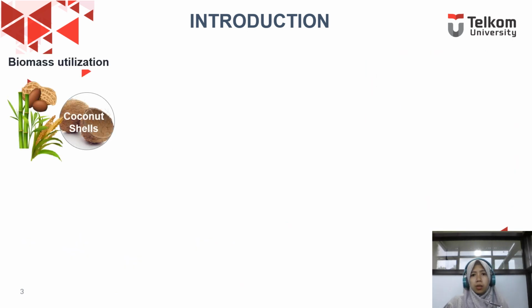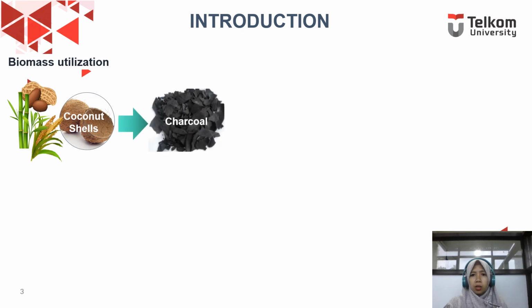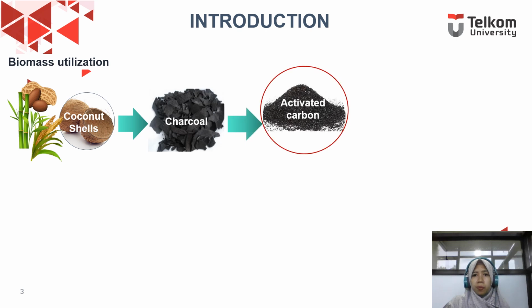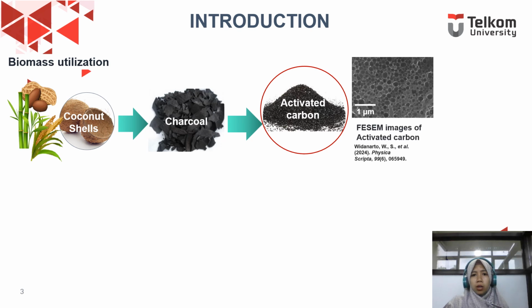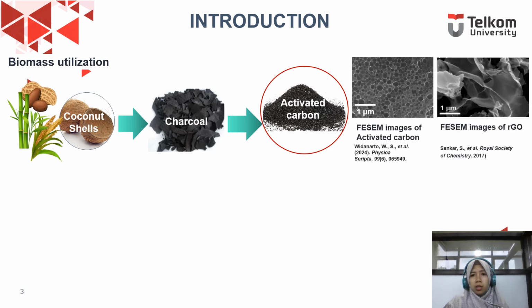Some studies reveal that biomass-derived activated charcoal or carbon has great potential to replace graphite in the synthesis of graphene. Coconut shell, when carbonized, produce the charcoal that is then activated, resulting in activated carbon with a higher carbon content compared to other biomass sources, as supported by reference. However, the morphology of activated carbon, which consists primarily of pores, differs from the sheet-like structure of graphene. Therefore, additional processing steps are necessary to produce